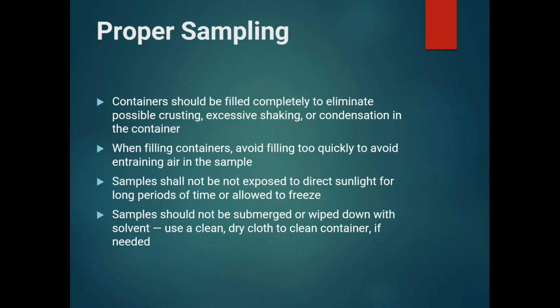And also, samples should not be submerged or wiped down with solvent. Again, the solvent that's left on the outside of that bottle can possibly contaminate the emulsion itself when we're pouring it up. And a lot of times these containers get put in water baths or ovens, and those can contaminate the water bath as well. Just use a clean, dry cloth to wipe off the container as best as possible if needed.